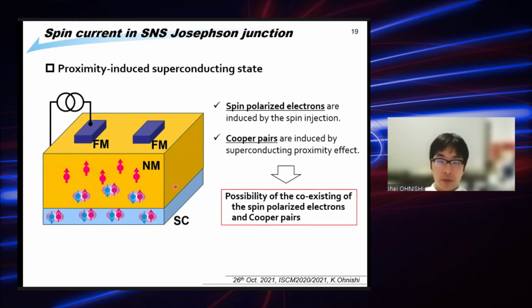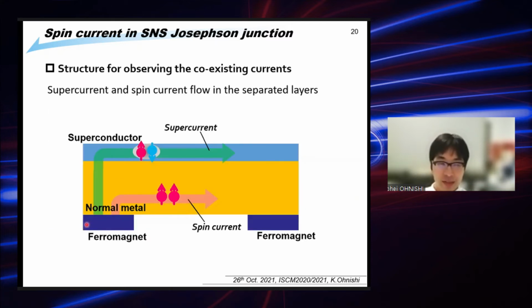We'd like to measure this situation, but for this structure, we turn it upside down. The bottom side is the ferromagnet layers, and the top is the superconductor normal metal bilayers. Okay, in this structure, the pure spin current flows in the normal metal layer, but the supercurrent flows only in the superconductor layer. So in this structure, we cannot confirm that the supercurrent and spin current can flow in the same layer.